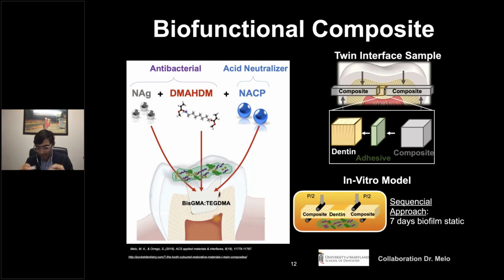That bonded material was actually exposed to challenges. The challenge was 7 days on biofilm culture. So what we did was prepare the beam, put it in a liquid culture of bacteria, multi-species. We got saliva from patients, and then we began to grow all of these species, and let them grow and form biofilms on the material.